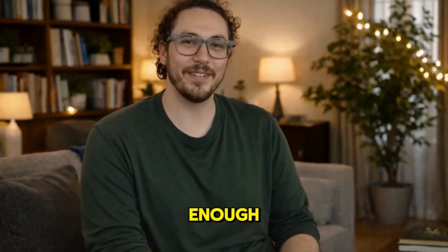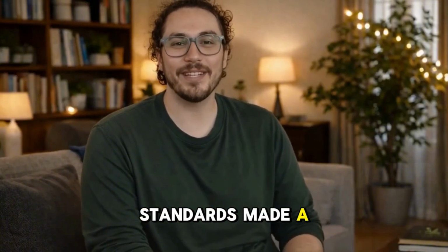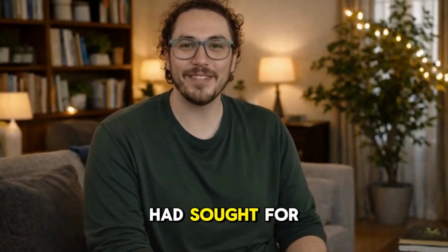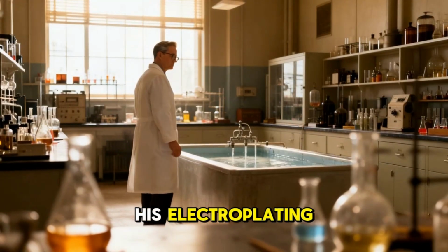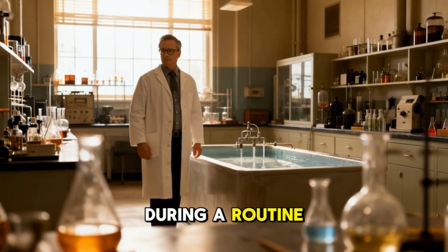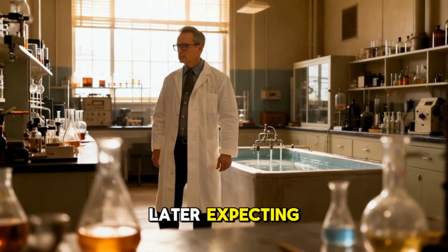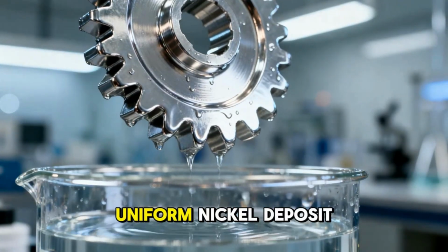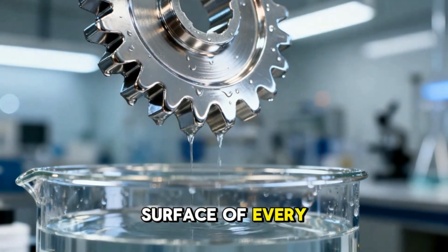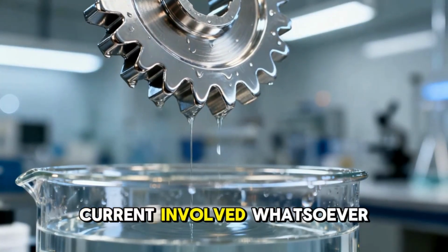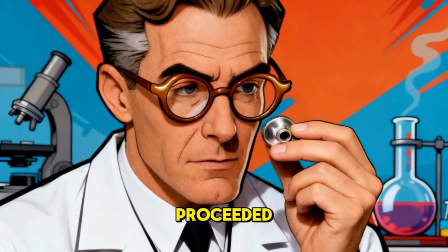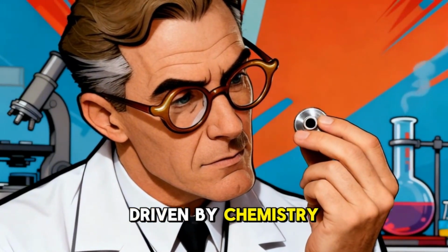In 1946, a chemist named Abner Brenner at the National Bureau of Standards made a discovery that formalized what craftsmen had sought for centuries. His electroplating rectifier failed silently during a routine experiment. He returned hours later expecting bare metal. He found a flawless, uniform nickel deposit covering every surface of every part in the bath with no electrical current involved whatsoever. The reaction had proceeded entirely on its own, driven by chemistry alone.